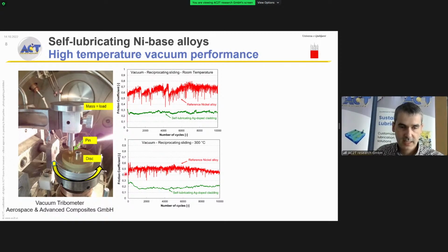And what we can observe here, so the reference nickel alloy in room temperature or at 300 degrees has a really high coefficient of friction, very unsteady with these spikes that are characteristic of metal-to-metal adhesion. And when we have the nickel-based self-lubricating material, we see that friction is very low, around 0.25 at room temperature and slightly below 0.2 at 300 degrees. So again, this is metal-to-metal contact in vacuum at 300 degrees without any lubricant at all.